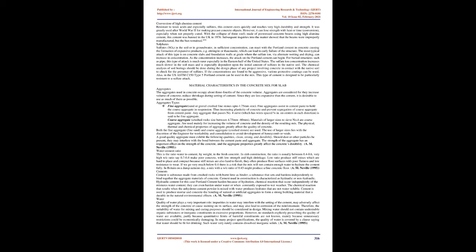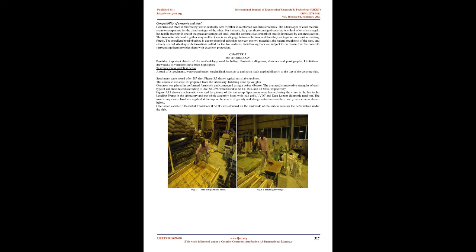The concrete then cracks either under excess loading, or due to internal effects such as early thermal shrinkage when it cures. Ultimate failure leading to collapse can be caused by crushing of the concrete, when compressive stresses exceed its strength, by yielding or failure of the rebar, when bending or shear stresses exceed the strength of the reinforcement, or by bond failure between the concrete and the rebar.